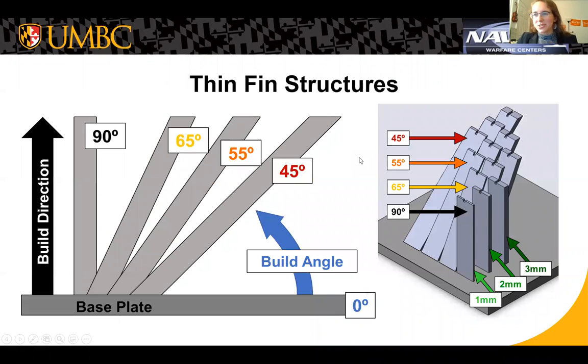So here's some more information on the thin fin structures. They're built at a 45 degree, 55, 65, and 90 degree build angle, as well as 3 different thicknesses, 1 millimeter, 2 millimeter, and 3 millimeter. We want to see how that impacts a variety of properties.